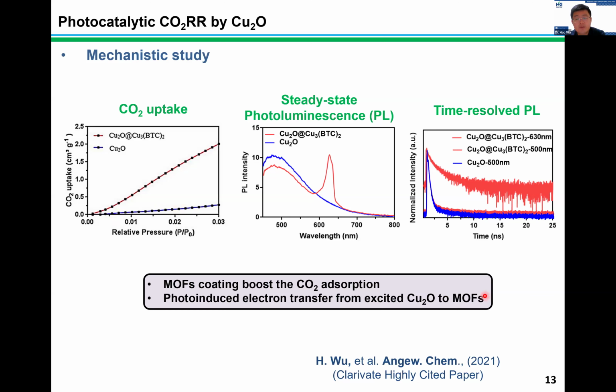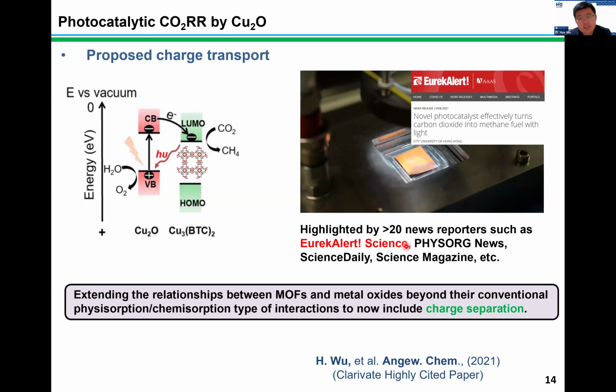This is a very important finding. It suggests that the electron can transfer to the copper MOF, and then the electron can be utilized by the copper MOF and react with adsorbed carbon dioxide to promote the carbon dioxide reduction reaction. So as a fundamental study, our research also extends the relationship between metal organic frameworks and metal oxides beyond the physical adsorption and chemical bonding types of interactions to now include charge separation. And as a proof of concept, our work ignites quite comprehensive attention from the community.